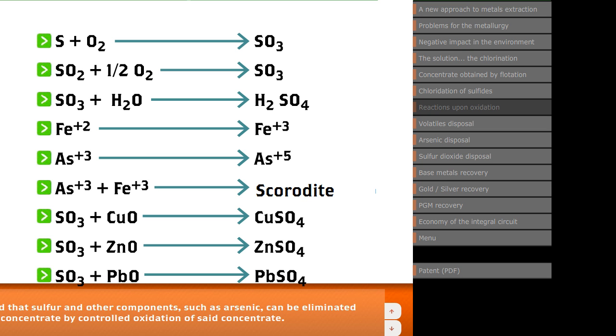We have found that by diluting the air feed with flue gases, it was possible to maintain the oxygen content of the air feed to about 10% oxygen instead of the 20% in undiluted air. In that fashion, with a temperature control that does not exceed 600 degrees Celsius, the oxidation is complete and exothermic. That is, it does not need fuel other than the sulfur in the concentrate, and leaves a solid residue with a very open structure, amenable to leaching.